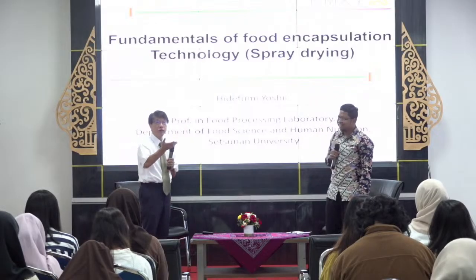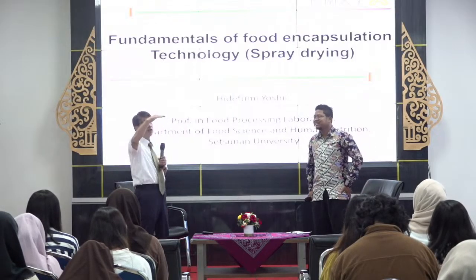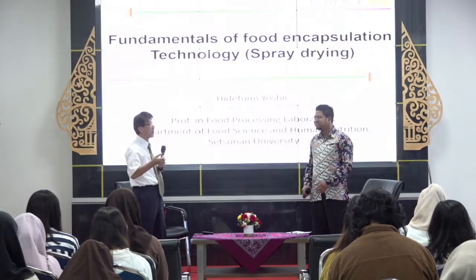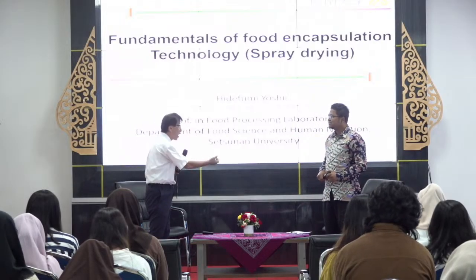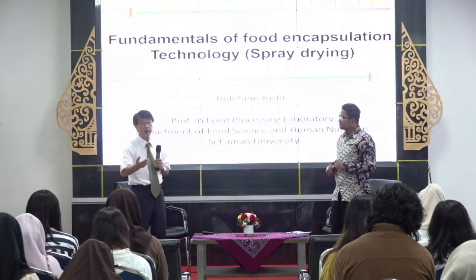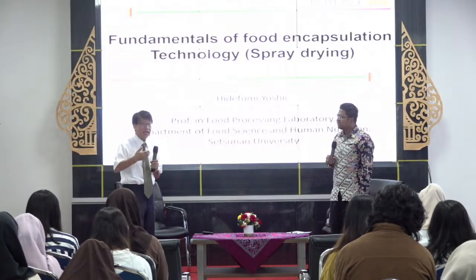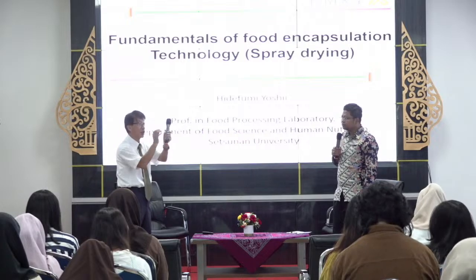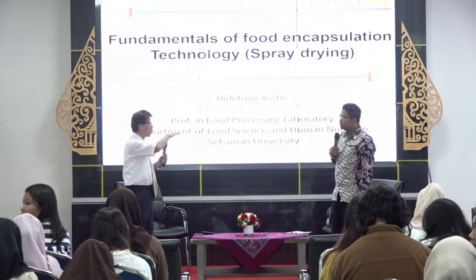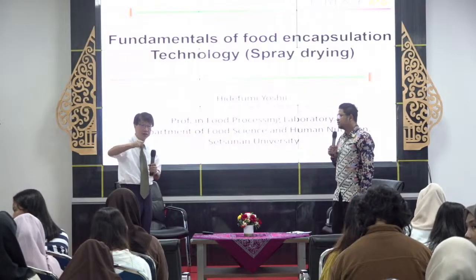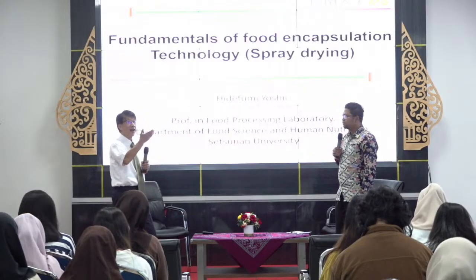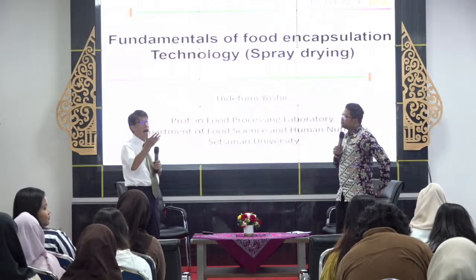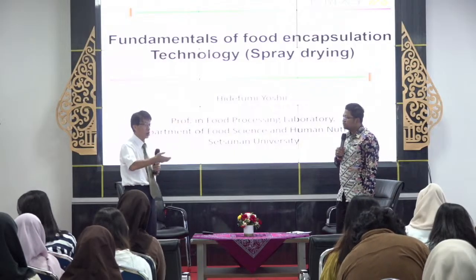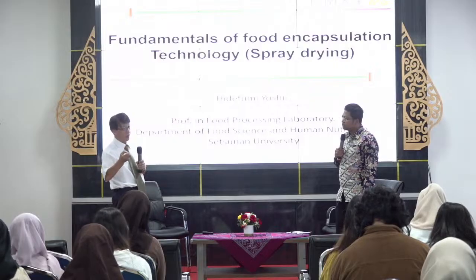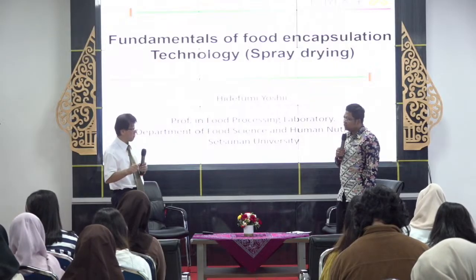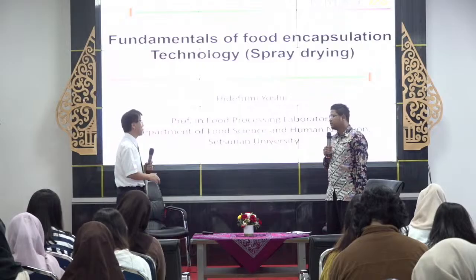So, for example, in the spray drying case, with a low glass transition material, we cannot get dried powder directly. We get some kind of aggregated condition, and then it is milled. Therefore, in the spray drying case, after drying, we have to make small powder using the mill. So the milling process is very important.